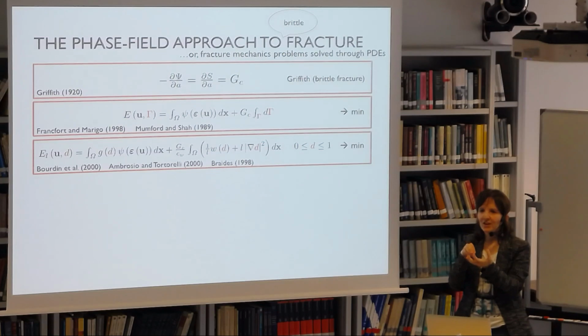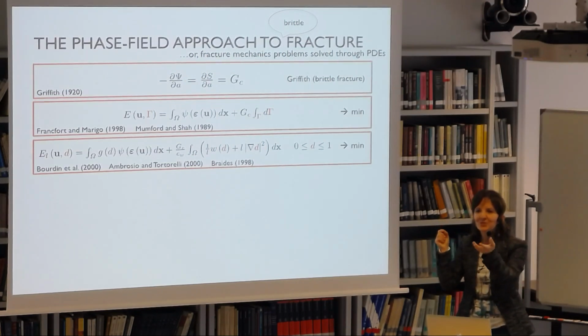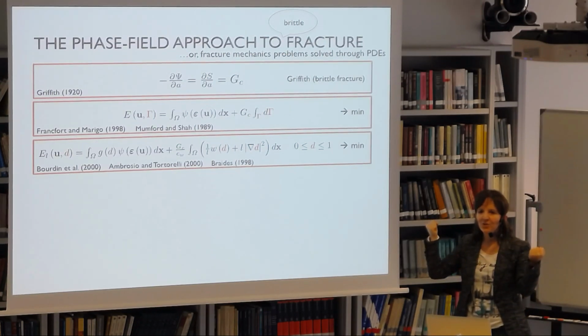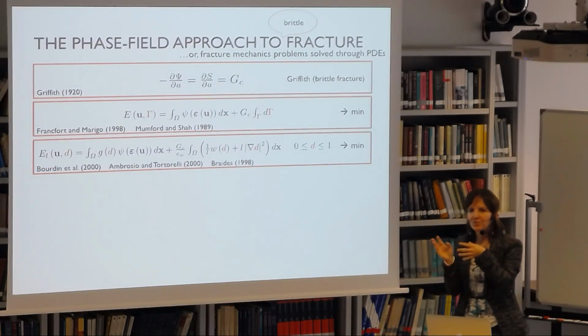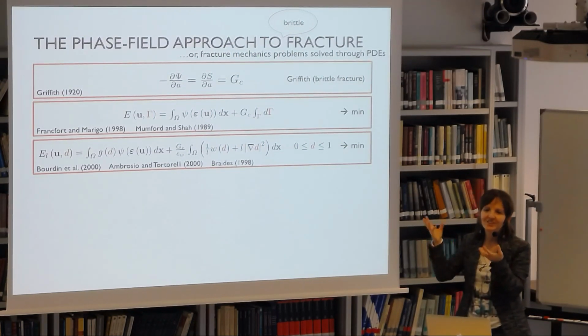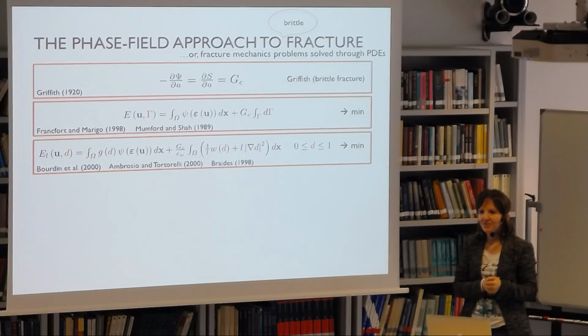So basically, the interesting thing is that in the expression for this critical stress, as we call it, L is at the denominator. So if L tends to 0, this critical stress tends to infinity, which is exactly what Griffith was saying. He was saying you can apply an infinite stress in a material without a crack. And this is exactly what you recover in the limit case of L tending to 0. But the fact that L is not 0 in this approach gives you this additional richness that allows you to describe nucleation as well. Okay, thank you. I agree with your answer.